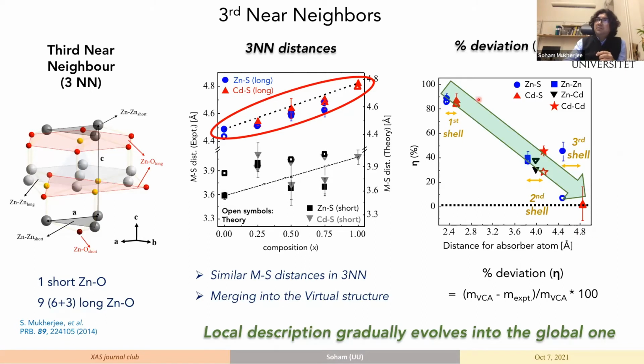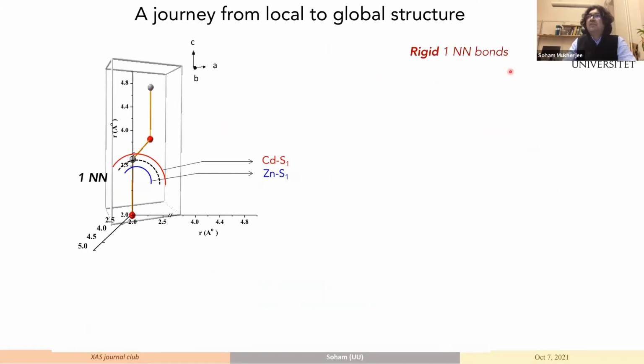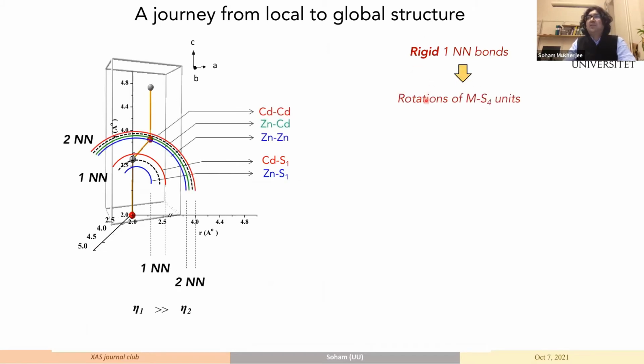And this we have shown periodically: you go from the nearest neighbors to the next nearest neighbor to the third nearest neighbor, and there is rotation of the bond angles. So basically what the system is doing is that you are putting in a different ion at one particular site, and the system changes its angle to accommodate the change in volume. And eventually at one length scale, it matches with the global description. So we have rigid first near neighbor distances, and then we have rotations of the MS4 units. And then this distance, cadmium sulfur one to zinc sulfur one,